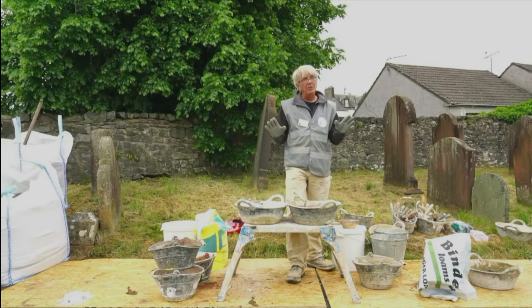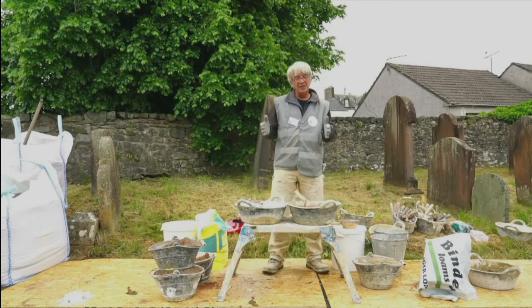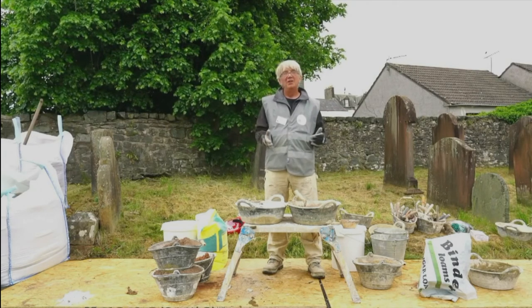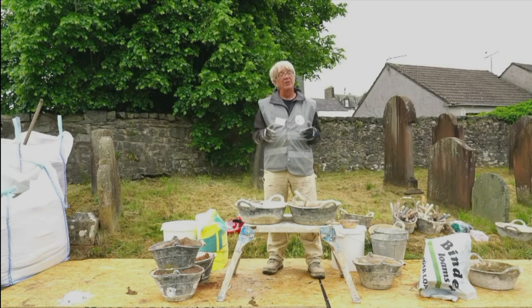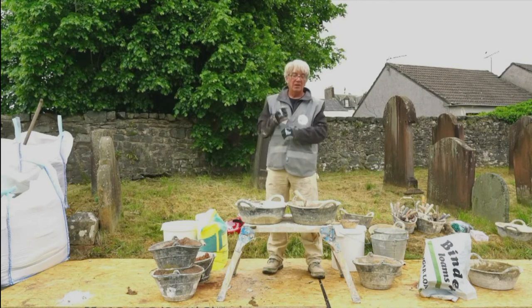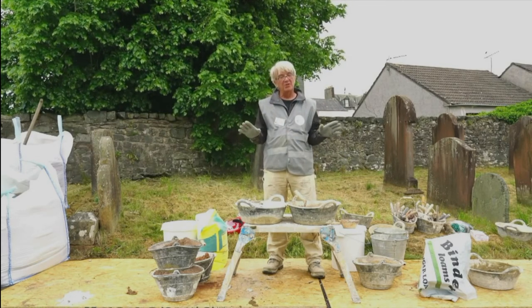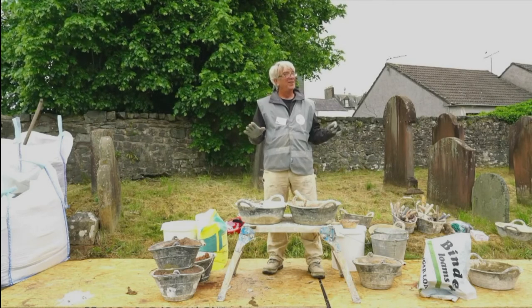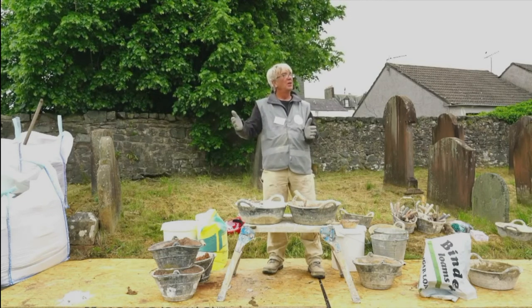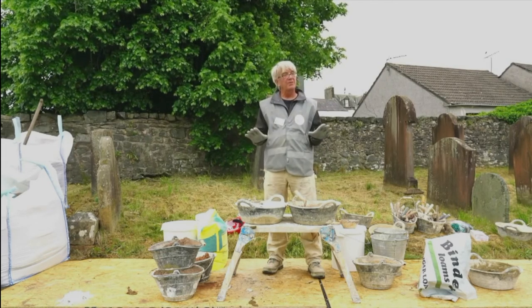But don't think this is just a little bit. When they put figures on it, a typical cubic metre of mortar, they will say needs to be beaten and pounded for 8 hours by two men. I mean, that's a lot. The reason for it, as far as we can work out, is that they'll always say a well-beaten mortar would be a stronger mortar, and you pound it to workability. Whereas in the modern industry, we use water to increase workability. They're specifically not wanting to put more water in, because of course that translates into more initial shrinkage. And you can bring it to that workability when it's got less water in by pounding it. There's only one piece of research that's been done on this.